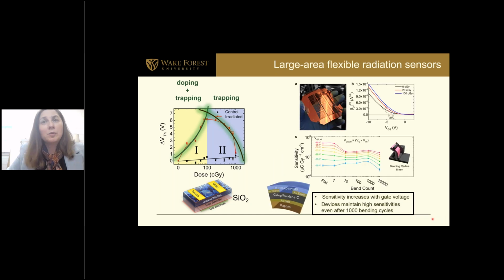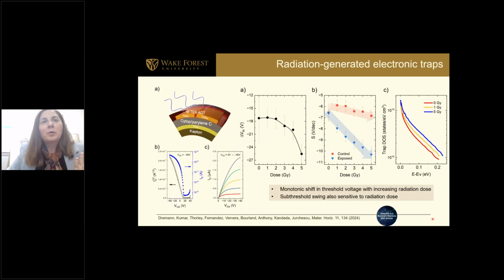We took these devices, we flexed them, they respond very well to radiation, and we tried to also understand what's happening in the material such that it makes it respond to radiation. So we performed the trap distribution of states analysis as a function of radiation dose, and you see that here.